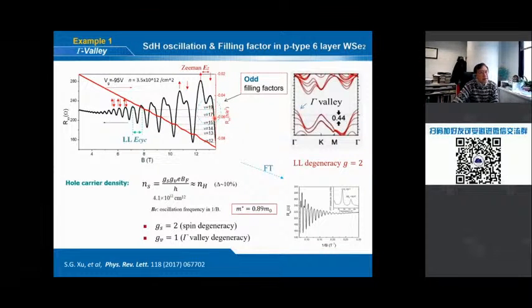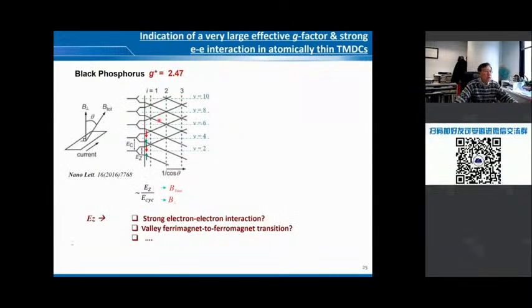If you look at the filling factor, it's a little bit strange. You have odd filling factors. In the last slides, I said normally it has paired states, and this should be an even filling factor. Why does it have an odd filling factor? That already indicates the unusual states in this material. I give you this figure to show the principle of how to measure the ratio of Zeeman energy and cyclotron energy. If the Zeeman energy is not large, I mean the G factor is not large, then you can actually use this figure to show that the filling factor is even.